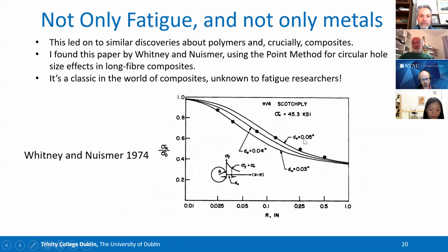Again, these D values here, we're predicting the strength of a piece of fiber composite laminate material as a function of the size of a circular hole in it. And the data is coming down in just the same way as you see in fatigue. And these D values are critical distance values. And he's finding an optimum value of 0.03 inches in this particular case.